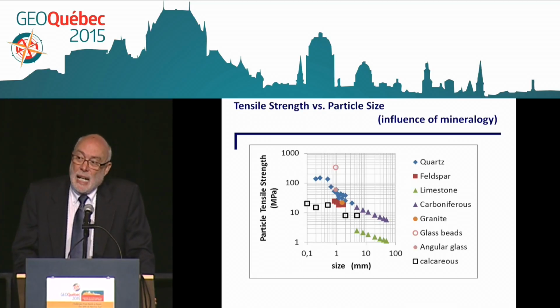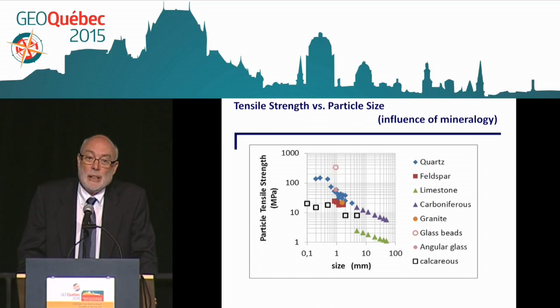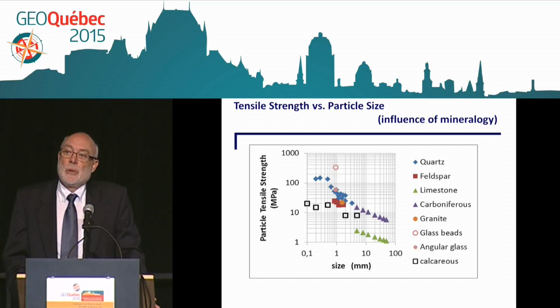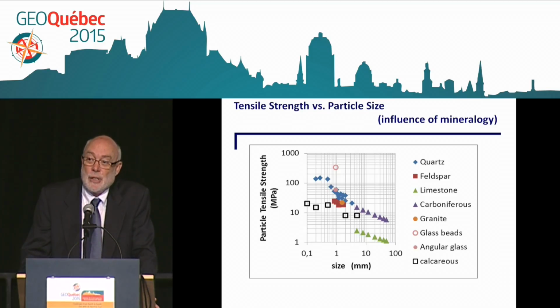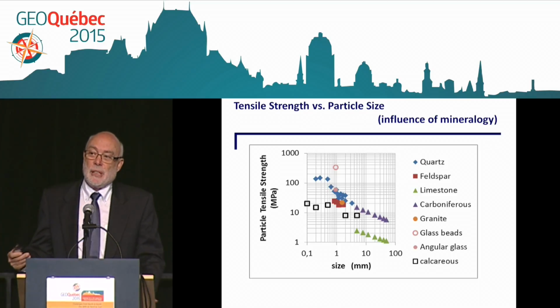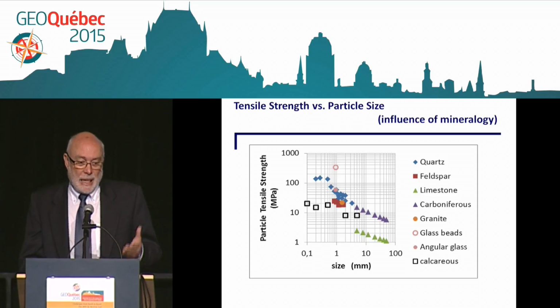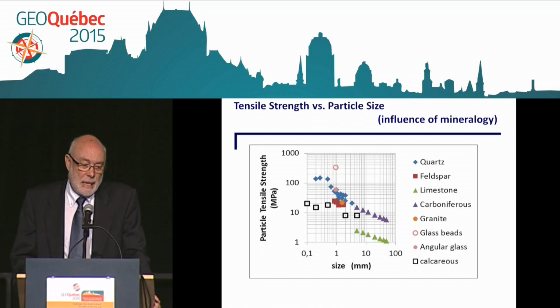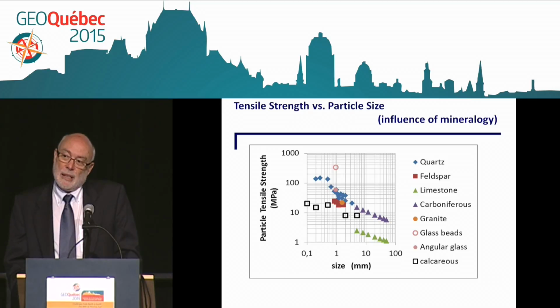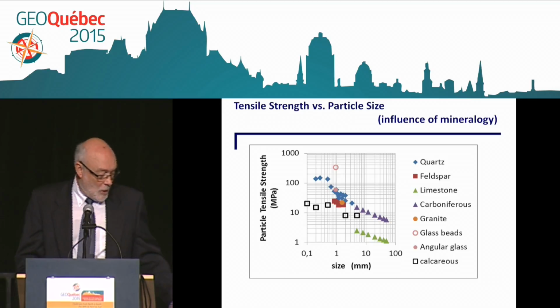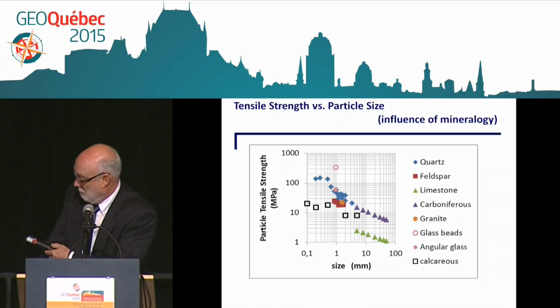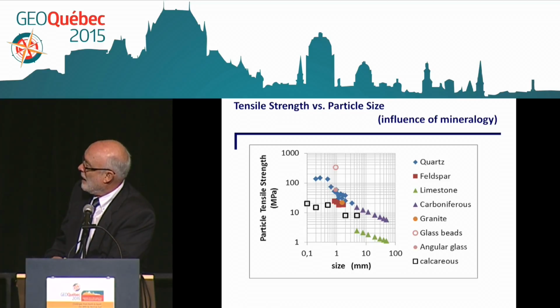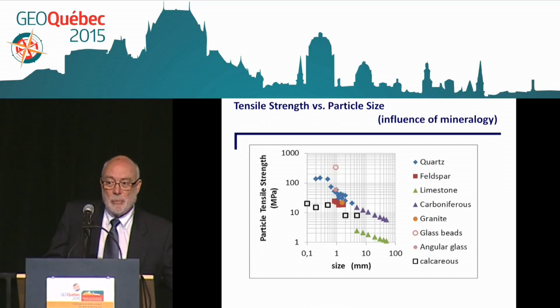Now, we also scanned over 70 years of literature on the topic. This topic has been studied since the early 40s, out of curiosity first, and as the decades passed, we got more and more interested in looking at it from an engineering point of view. But it is clear that the mineralogy of the grain plays a great role, and you see the strongest mineral is quartz, and the weakest would be limestone, the green triangles at the bottom of the graph. And we also see that this is angular glass, and this is glass beads. Again, the shape of the particle plays an important role.